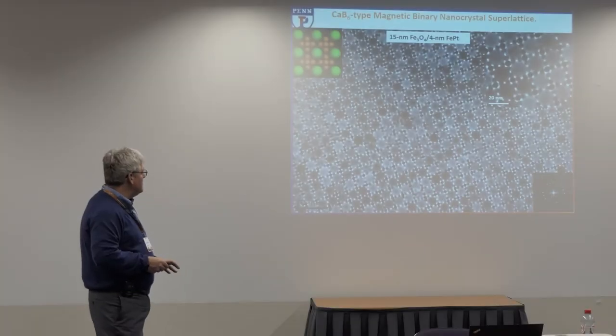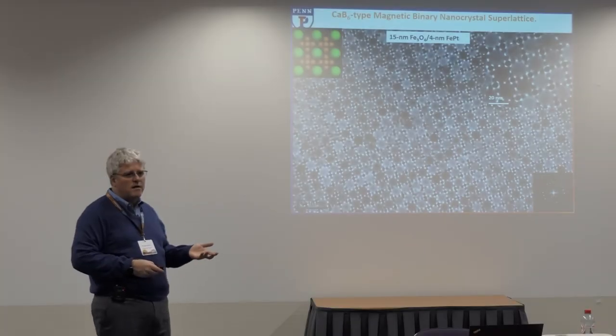And actually, very high performance neodymium iron boron magnets and other systems that you probably do experience in your lab life, they actually have a natural structure that looks not as regular as this, but that's the origin of the high performance in those systems. Through the metallurgy, they're heated, and natural precipitation on fine length scales results in little pockets of different compositions. Some of those pockets are high moment material, and some are high coercivity material. And it's the spring coupling through the exchange, it's exchange coupling that gives a spring effect that holds those pieces together.